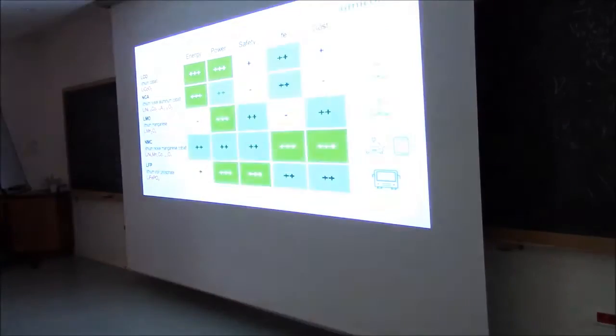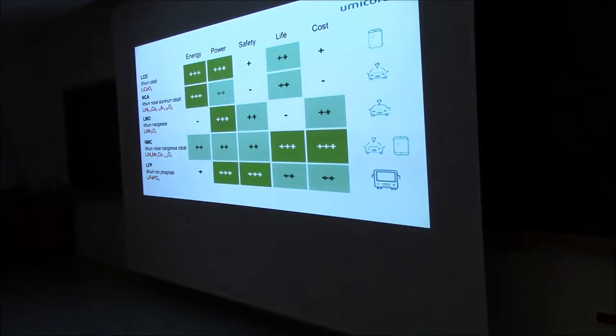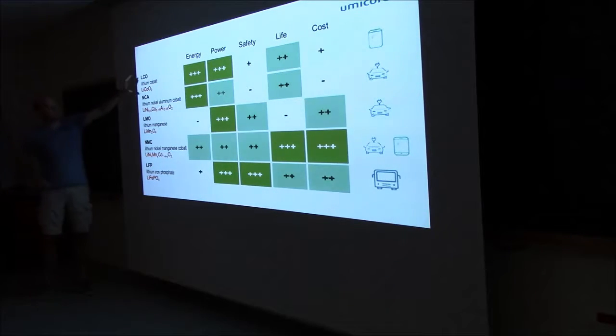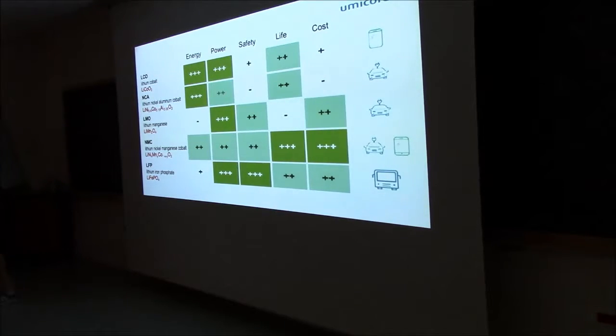And these are some of the pictures which they were doing in the last couple of years. Of course, I don't have an idea of what they will be using in the coming years, but you can see there are differences between them depending on which part they found most important. So this is what I discussed. Lithium cobalt oxide, energy power is okay. There are some other issues. This is what Tesla was using. Lithium nickel, aluminum cobalt, lithium manganese, NMC. And this is the one which is also interesting, which is called LFP, lithium iron phosphate.